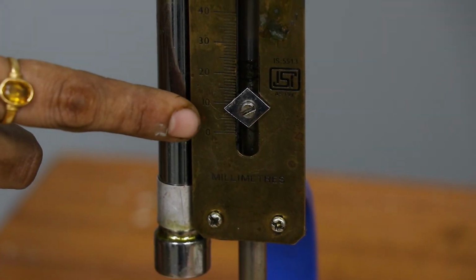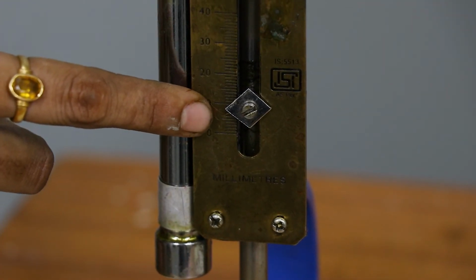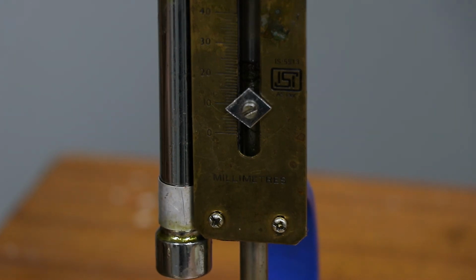The penetration comes out to be 7 mm for the 31% of water we have taken to prepare this cement mix. This indicates that 31% is the standard consistency of this cement paste. The 31% standard consistency will be further used to carry out the other tests on the cement.